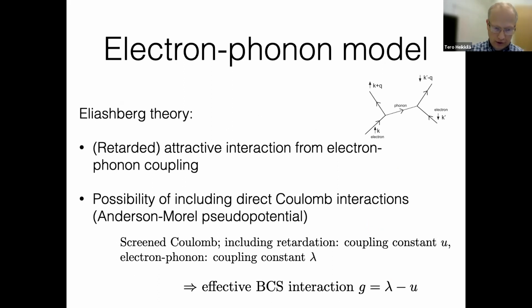Okay, so this was the instantaneous interaction where you just assume that there is some attractive interaction. You can also do the Eliashberg theory properly for these flat bands, in which case you consider the electron-phonon coupling and you get a self-consistency equation from the electron-phonon self-energy, and this approach also allows you to include direct Coulomb interactions via the so-called Anderson-Morel pseudopotential trick. I have some slides to show if there are questions, but otherwise I will just give you the conclusion of this consideration.